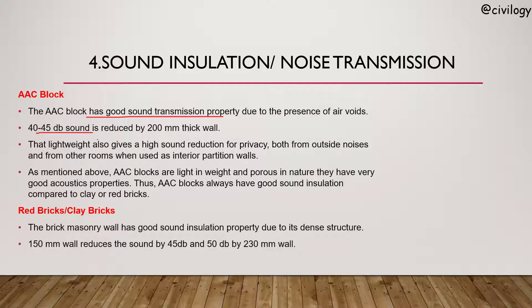Sound insulation: AAC blocks have good sound transmission properties due to the presence of air voids — a 200 mm thick AAC wall reduces sound by 40 to 45 decibels, providing high sound reduction for privacy from outside noise and between interior partition walls. For red bricks or clay bricks, a 150 mm wall reduces sound by 45 decibels, and a 230 mm wall by 50 decibels. Both are good sound insulators.